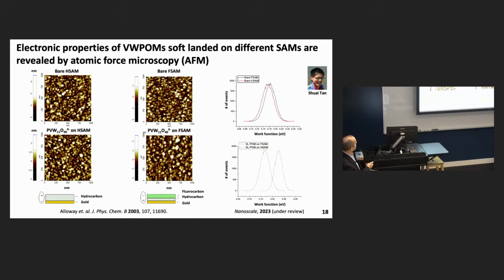And what you can see on the top is that before deposition, these clusters have very similar work function, but after deposition, there's a split basically in the properties of these two layers. And we believe this is because more charge is retained on the fluorinated monolayer. So you have greater Coulombic repulsion, which makes that electron easier to remove than on the comparable other surface.